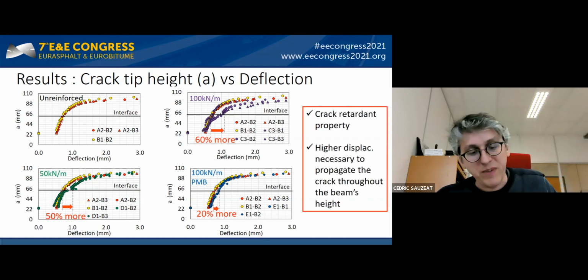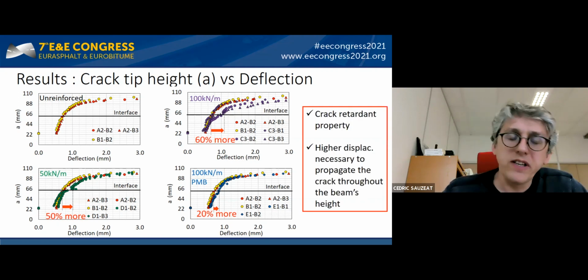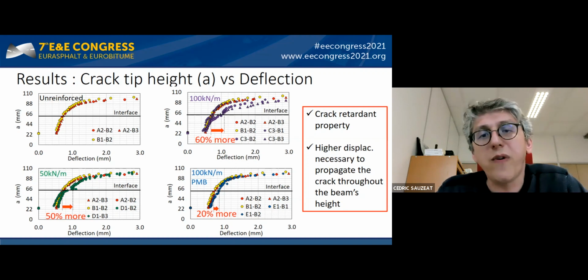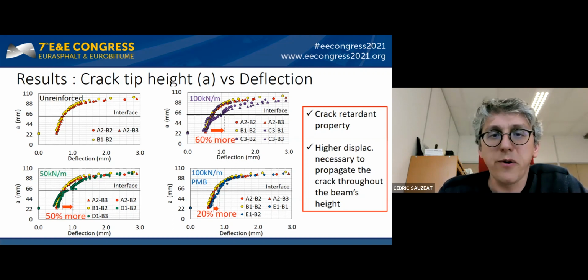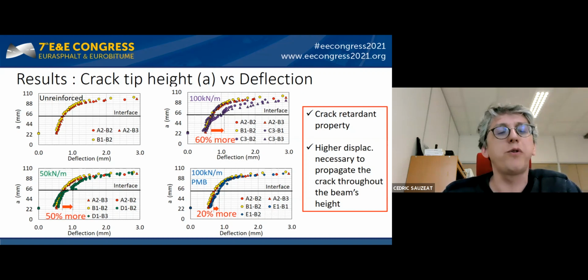So from these results, the geogrid shows to be a crack retardant for the crack propagation. And you can see that you need to apply higher displacement to propagate the crack throughout the beam height.